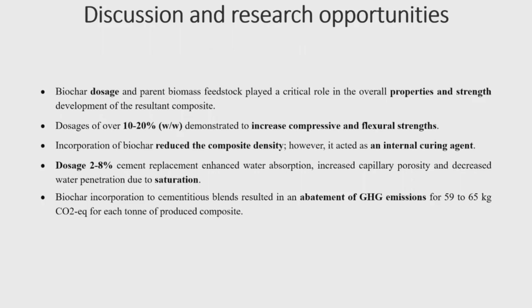Well, the main findings of the present review were that biochar dosage and parent biomass feedstock played a critical role in the overall properties and strength development of the resultant composite. Temperature, feedstock, the involving conditions, and the dosage are really important aspects when one is trying to develop eco-efficient cementitious composites which still compete with conventional blends. The second thing would be dosages of over 10 to 20% on a weight basis, demonstrating to increase compressive and flexural strengths.